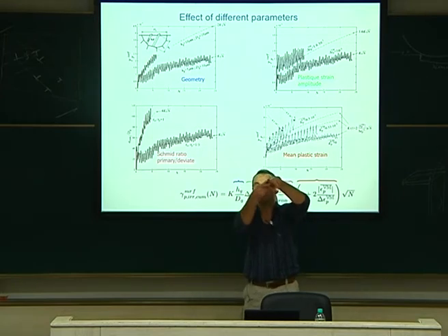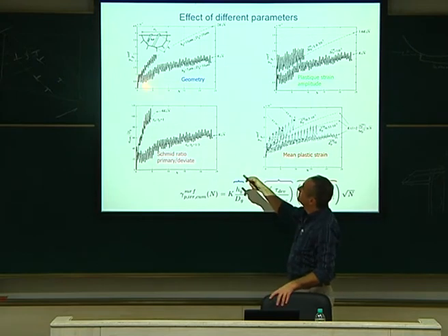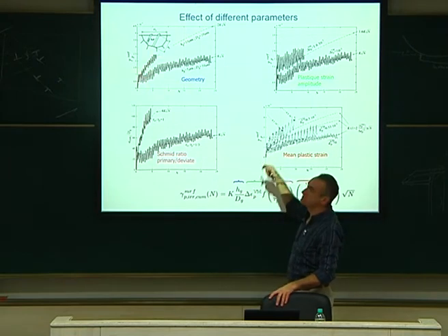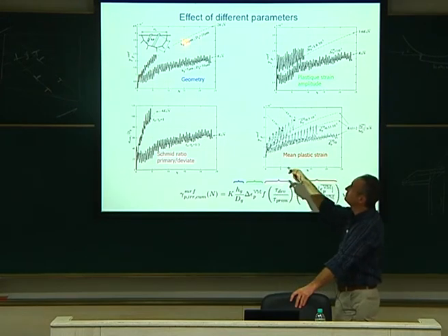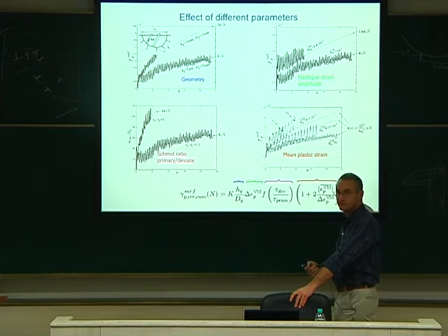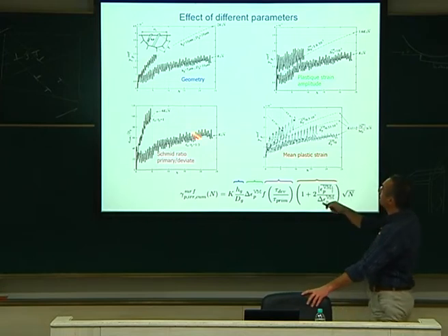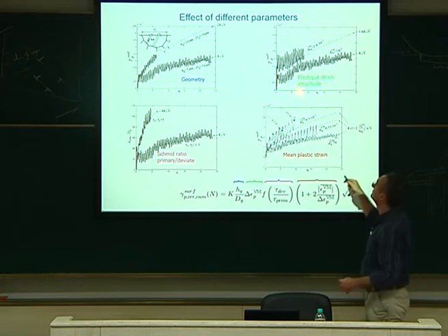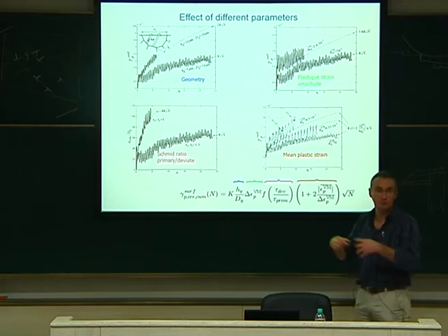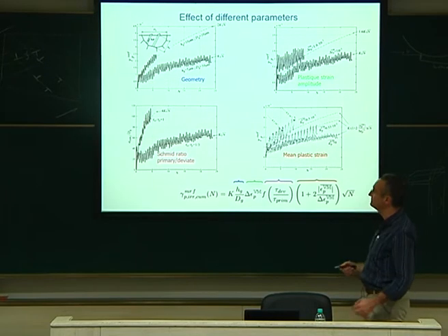So if it doesn't remove the step, it means that you will have a higher irreversibility for deeper grain. Okay? So the deeper the grain, the worse it is for the fatigue life of the material. This is a first example, okay? Then we can do the same for many other parameters. Here, for example, is the plastic strain amplitude. Here 10^-3 and here 1.6 times bigger. Of course, the more you apply the strain, the worse it is. The more you create irreversibility.